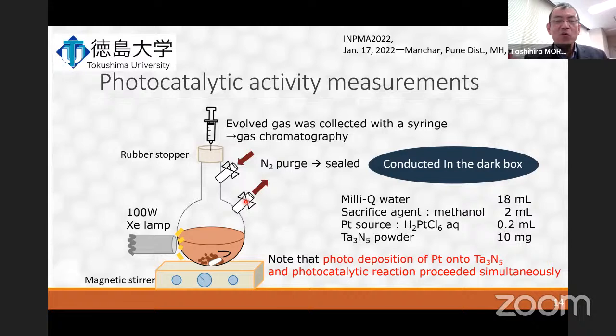A xenon lamp was used for the photocatalysis and photodeposition of Pt onto the catalyst. Hexachloroplatinic acid will be photodeposited on the catalyst. Note that the photodeposition of platinum onto tantalum nitride and the photocatalytic reaction proceed simultaneously in this experimental condition. Sampling was conducted every 1 hour. The product was analyzed using gas chromatography equipped with a thermal conductivity detector and a packed column with N2 as the carrier gas, okay?